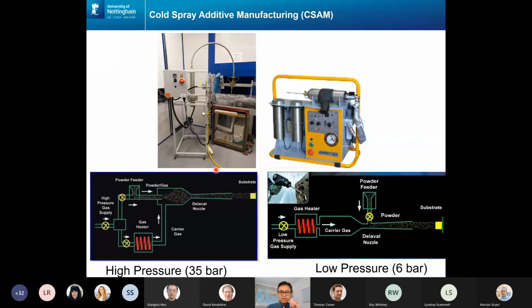So one of the things we use at Nottingham is called cold spray additive manufacturing. So this is a high pressure cold spray setup, goes up to 35 bar. And this is a low pressure cold spray setup, which is around 6 bar. In a high pressure cold spray, we inject the powder and heat the gas up, and we're using cheap gas like nitrogen. And these particles travel in excess of 700 meters per second. When they hit the substrate, they deform and stick to each other.